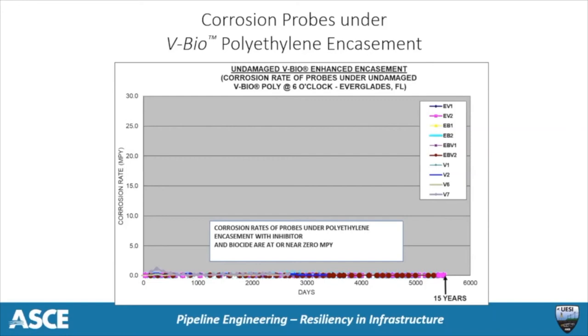Here is a similar plot of readings, in this case 15 years of readings of corrosion probes under V-Bio enhanced polyethylene. As you can see, from day one, no discernible corrosion rates were measured, which has continued to be the result to this day.